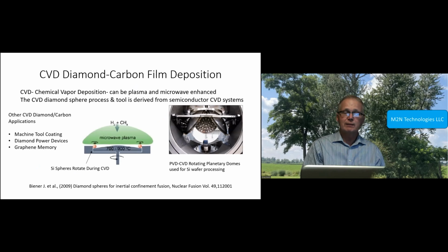The chemical vapor deposition process is typically plasma or microwave enhanced. This again is a modified tool leveraging machine tool coating, diamond semiconductor power IC processing, and the graphene memory processes that were developed about a decade ago. So we're taking the same tools. Instead of using a planetary rotation like we would on the right for a wafer, we're rotating the spheres in little tracks with the methane hydrogen plasma above, which coats this with a dense carbon or diamond sphere.